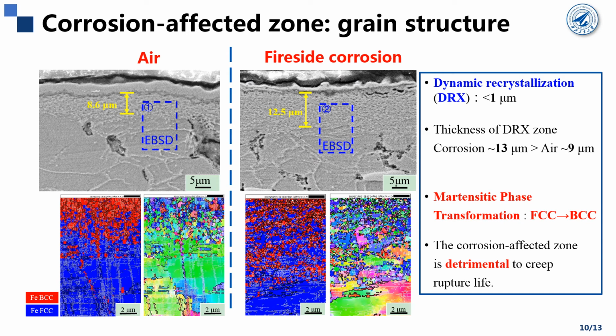In this page, in combination with the SEM images on cross sections, together with the EBSD mappings showing the phase structure distribution and the grain structure orientation, we're pretty sure that dynamic recrystallization occurs in both cases, which produces a large number of refined grains with an average grain size less than 1 micron. And the thickness of the recrystallization layer in corrosion environment is apparently larger than in air condition. That is 13 micrometers versus 9 micrometers.